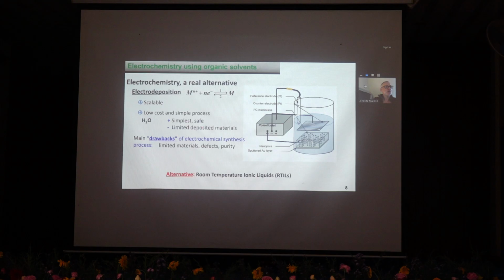So electrochemistry is a very versatile method which is suitable for a wide variety of materials. It's scalable, easy to translate to large scale, which is important for batteries. Very simple. However, it suffers from a big drawback, which is the electrochemical window of the solvent which is used. The main limitation relies on the use of water, because when we use water, we have a window which is limited to about 1 volt, between the water reduction producing hydrogen and the water oxidation producing oxygen.